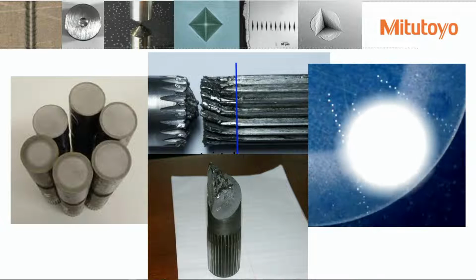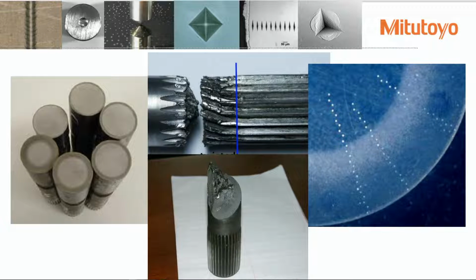Okay, this is about a 50x macro picture. This is what they would have done to figure out the case depth on there. They would have done a series of hardness tests, starting from the outside edge and working their way in. And when they finally got to the core, they would say our effective case depth is whatever, 50 thousandths or 100 thousandths or whatever it needed to be at that point.